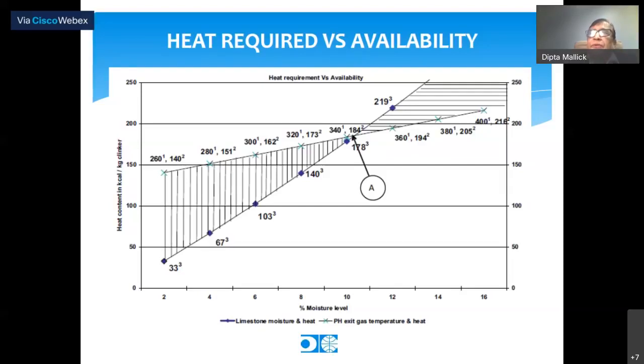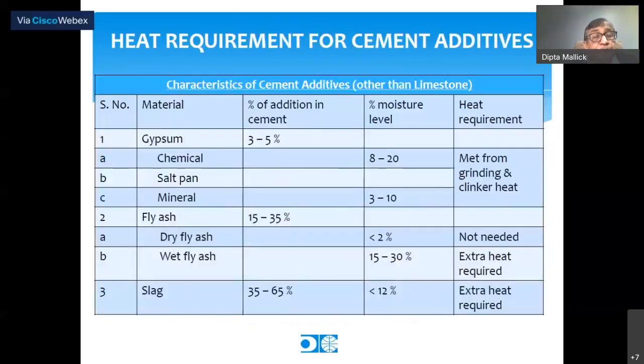But in most of the cases, we are operating in a range of 3 to 4% moisture in limestone. So that means we have plenty of heat. We have about, say, 100 kilocalorie per kg of heat available in the system for doing some useful purpose. Also, some heat is required for additives, and this chart gives the amount of heat that is there. That is not a very significant part.